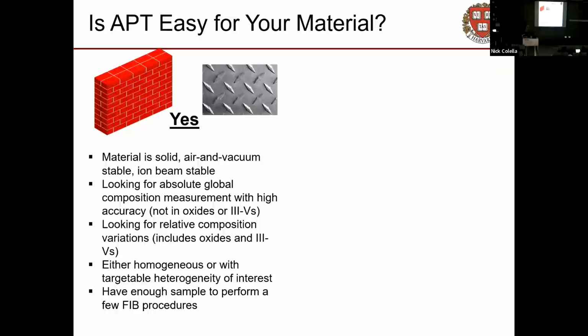Materials that are homogeneous, because the actual volume we're measuring is pretty small, a cubic micron, thereabouts. So if you're looking at a material where this cubic micron and that cubic micron are wildly different, you're going to have to do a lot of atom probe to get a meaningful, statistically powerful data set that you can actually work with.